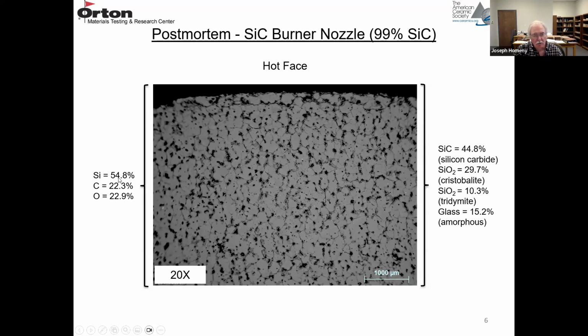So this particular material is about 55% Si, 22% carbon, and 22% oxygen. Because it is already oxidized, you have oxygen present. Normally, there'd just be silicon and carbon. So for the phases that are present, these were determined by X-ray diffraction. There's silicon carbide about 45%.